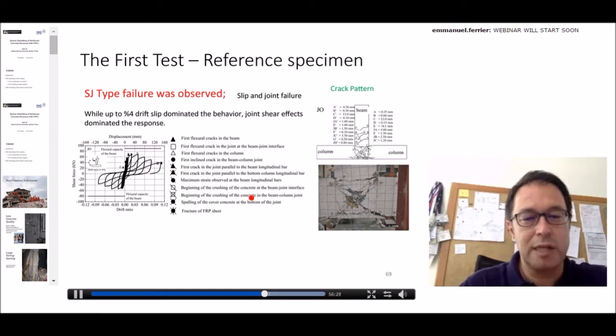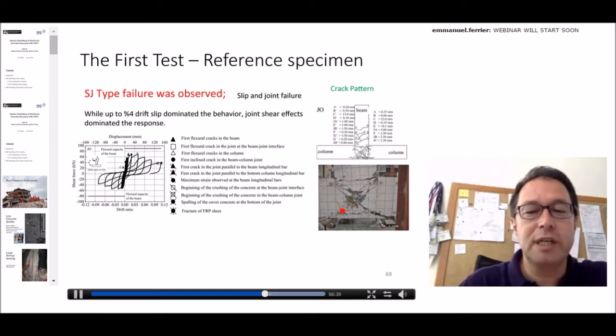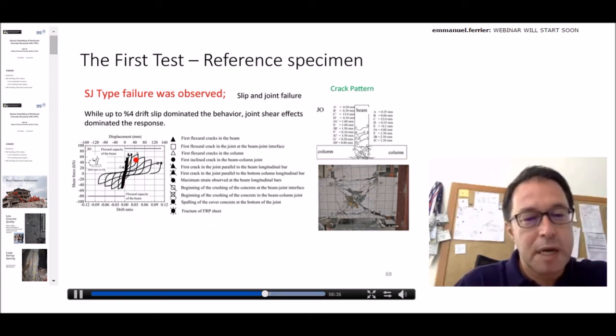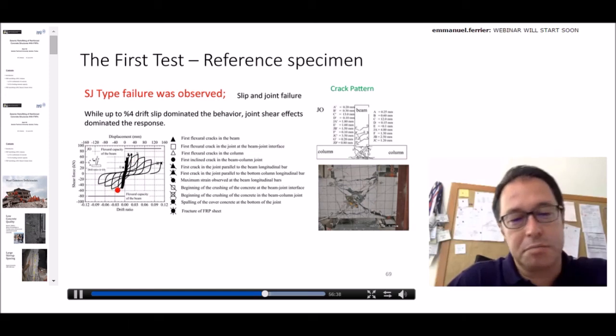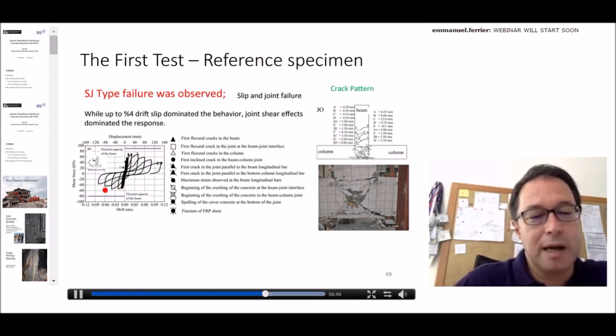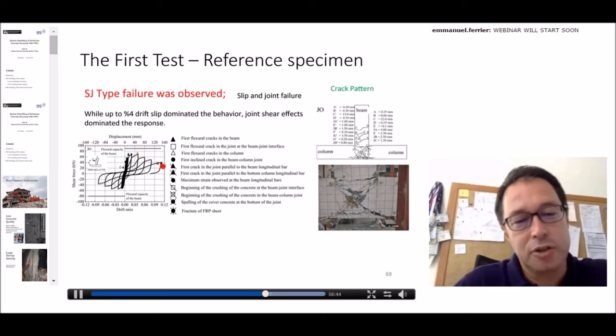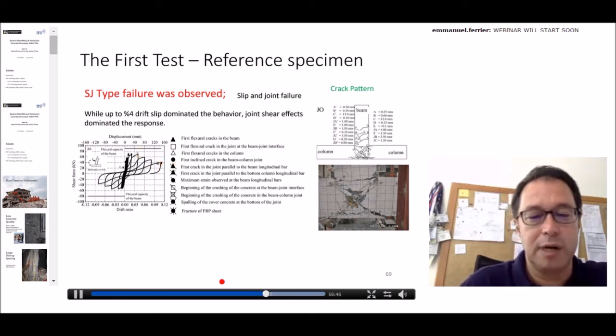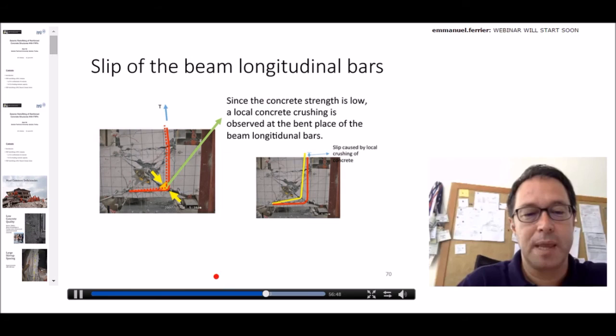And if we sufficiently retrofit the joint, then the failure should occur within the beam. So that's not a very bad behavior because it is quite ductile, even if it has less than the expected strength compared to shear failure. Still, we could go up to large drift levels. And this explains how the slip of main longitudinal bars occurred. That's a kind of strange mechanism.